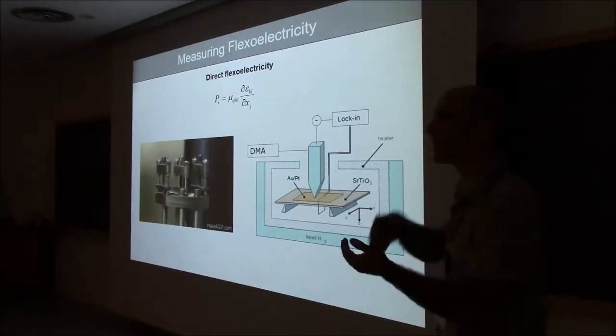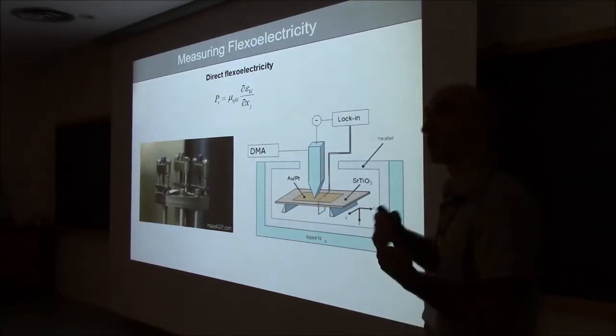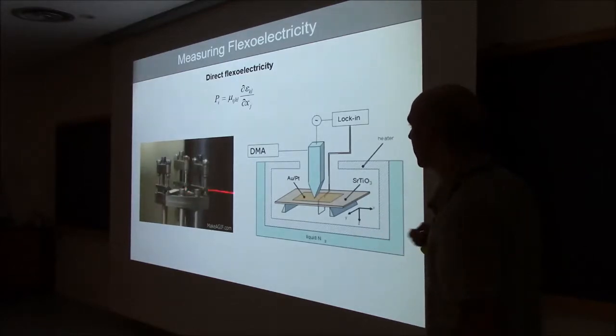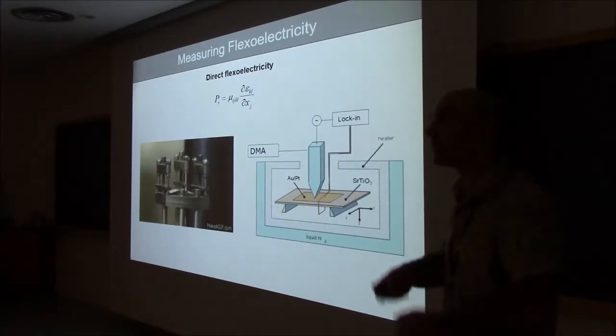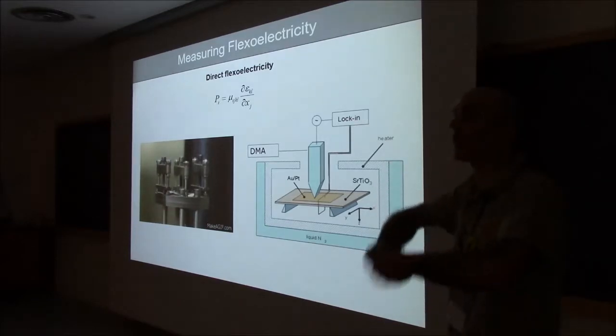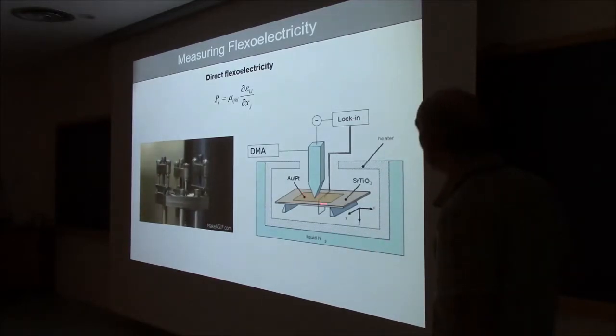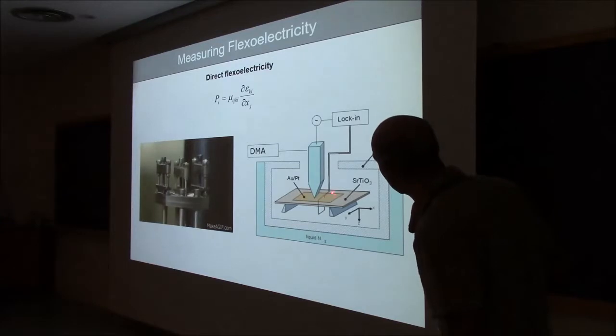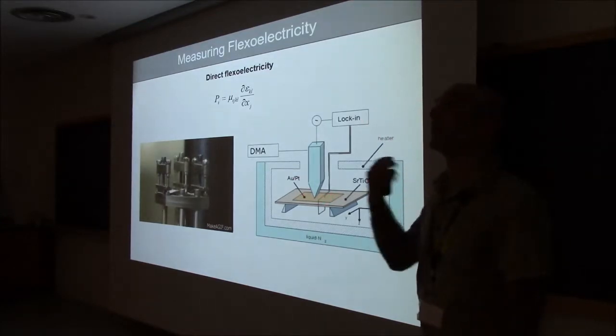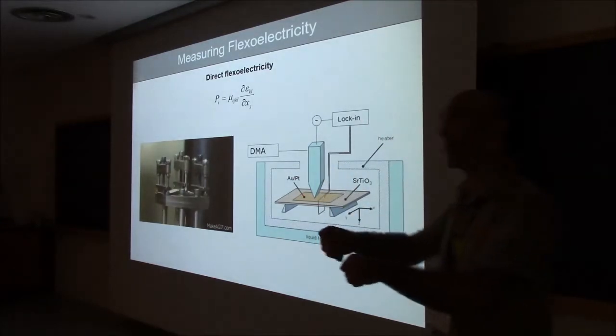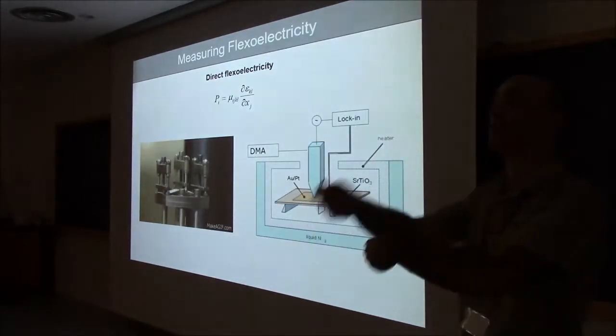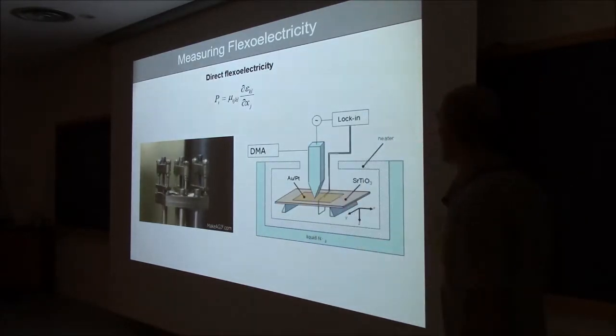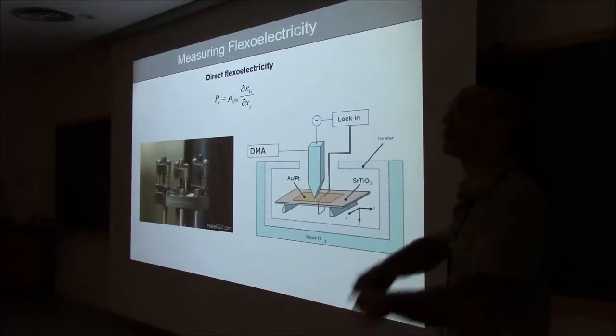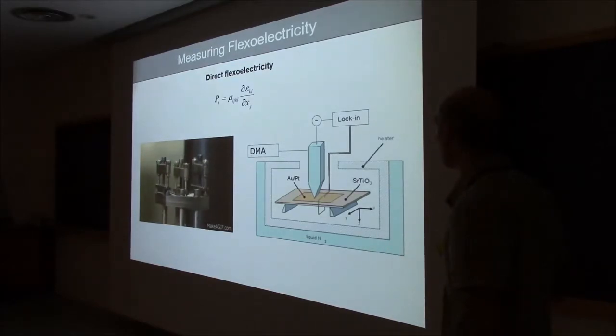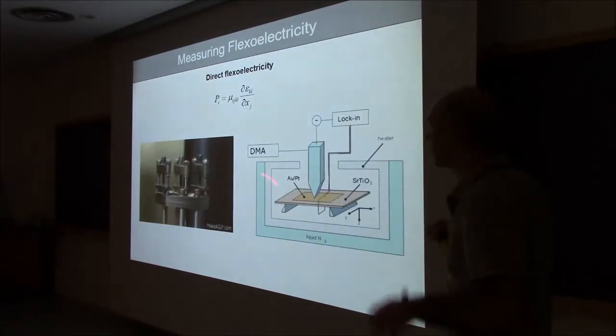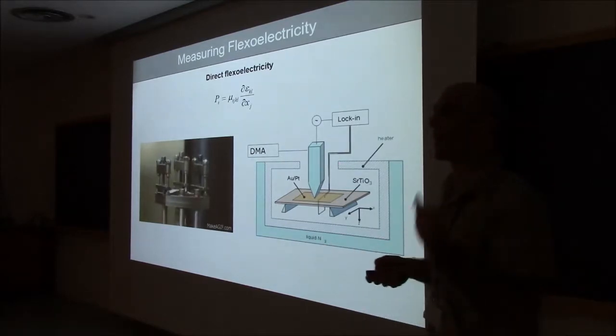This is basically something that applies a periodic force to whatever your sample is. If you put your sample in a kind of 3-point bending geometry, when you apply your periodic force, you get a periodic bending. If your sample has electrodes and you connect those electrodes to a lock-in, then you can measure the displacement current. Remember, every time you change polarization, you get a displacement current, and that's what we measure. We measure the displacement current induced by the bending. And in our DMA we can do measurements as a function of temperature.